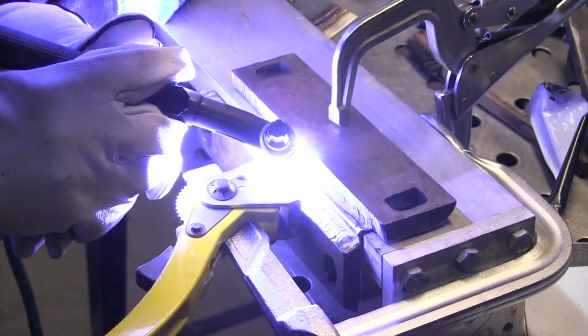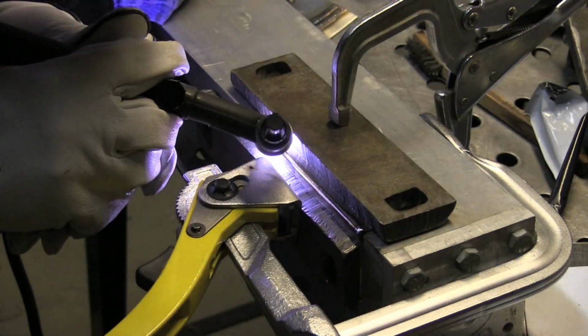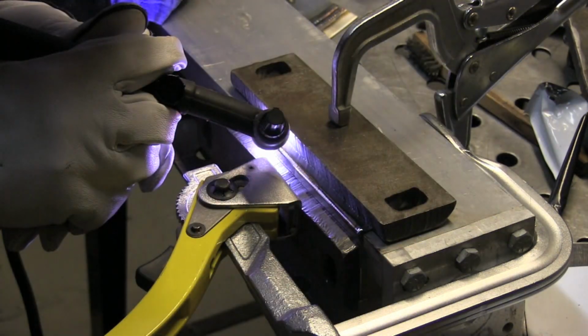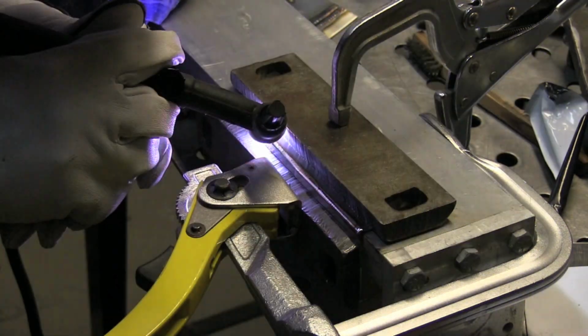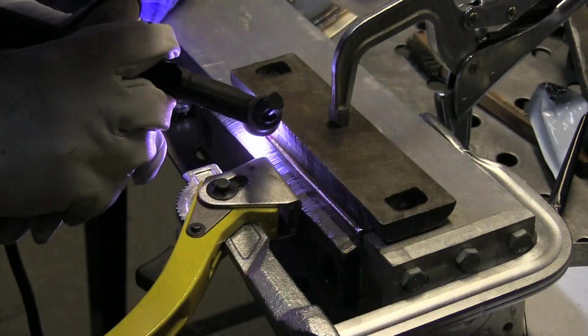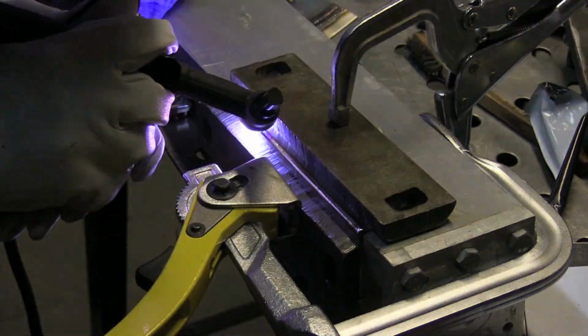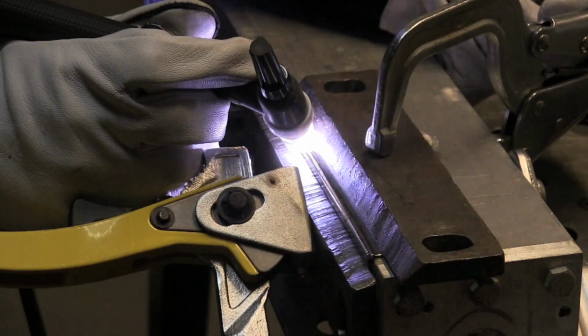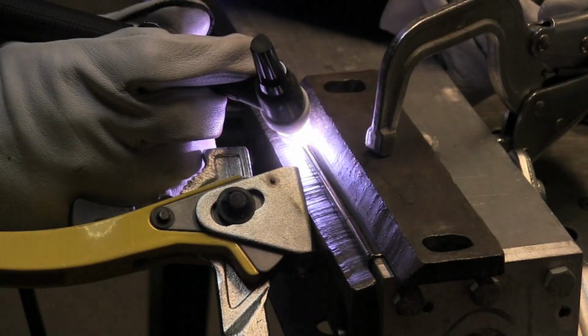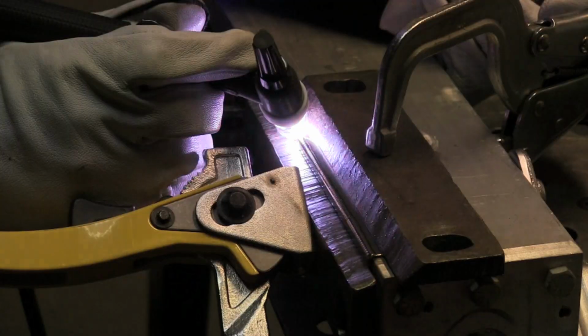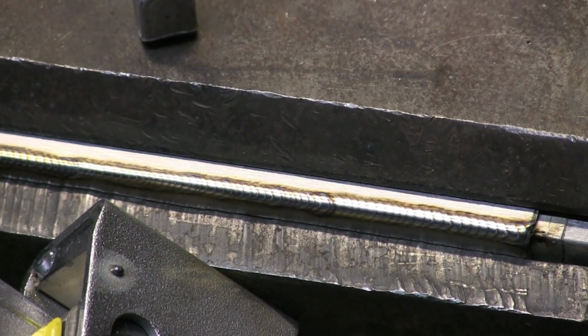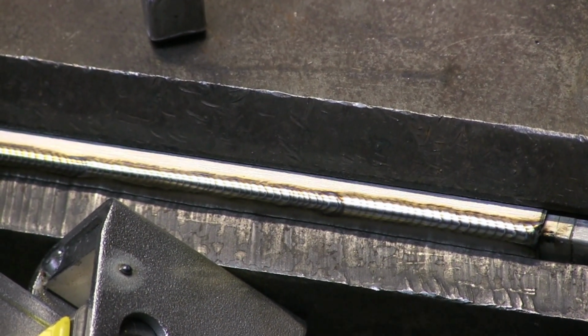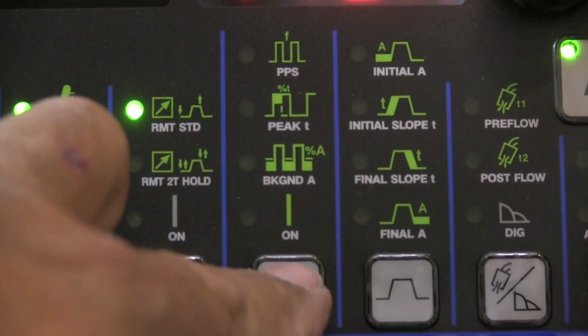I'm going to go ahead and run this piece all the way out to get a feel for it. This is set at those settings that Alex was talking about, 1.5 pulses per second. And it really is pulling the heat out of that stainless to the point that I'm getting almost zero discoloration out of this thing. And these are just carbon steel bars here. Ideally, if I could get some blocks of copper, that really pulls the heat out probably the best of anything for using as chill bars. But it's kind of hard to get a hold of copper. But even with the carbon steel, you can see it's almost no discoloration there. So it's doing a good job of chilling.